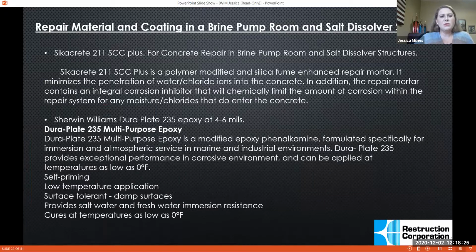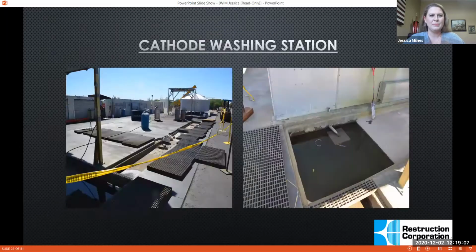What is noted that's different about this coating that could carry over into a mine or someplace like that is this coating was intended to be submerged underwater. So it is a marine type coating, but it also has the formula to withstand the salts and the different things that are going to be in the water that is in this structure. And then like I mentioned, the Sikacrete 211 SCC, that's a polymer modified and silica fume enhanced repair material. And yes, that's the same silica that we hear about with MSHA all the time.